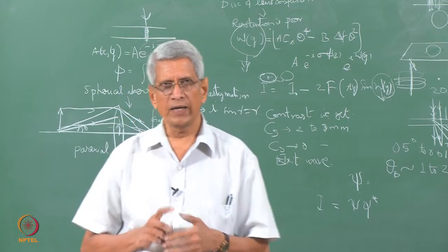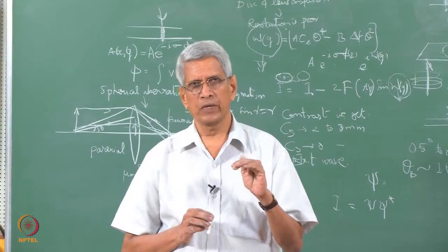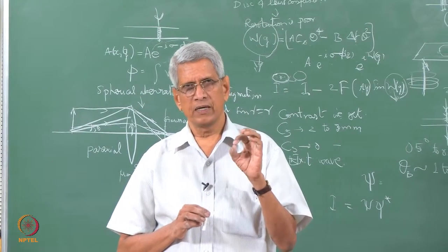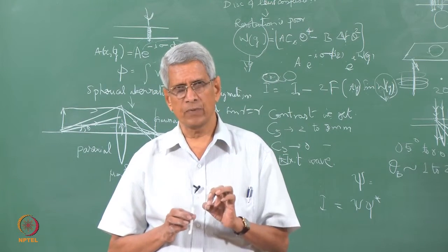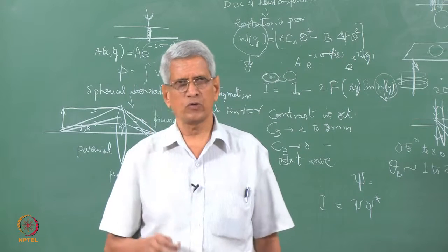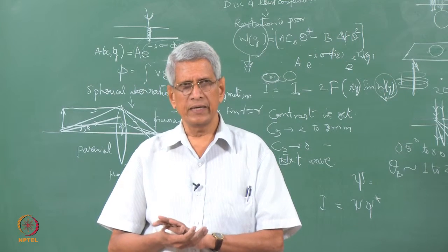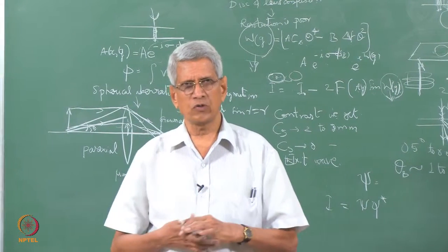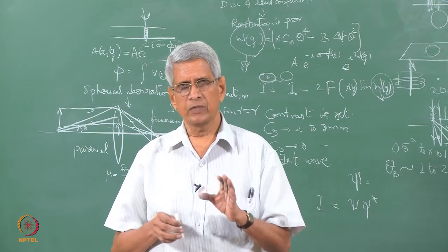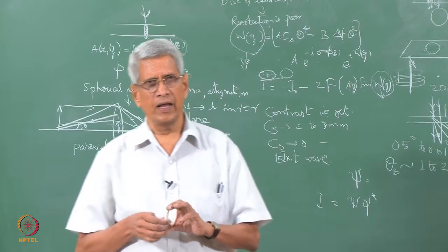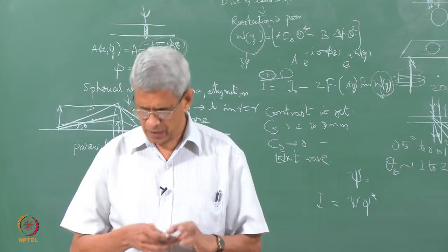To avoid this, the incident electron beam itself can be pulsed. A monochromatic beam is pulsed at a particular frequency, with a very small pulse duration, maybe nanosecond pulse duration. As the beam passes through that sample, you record both the image and the diffraction pattern. And then progressively as the beam passes through that sample, we can get information about how the electron beam is modifying the sample. That information could be obtained.